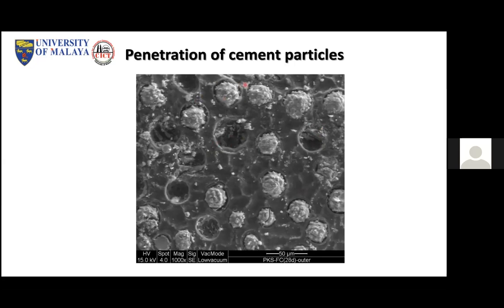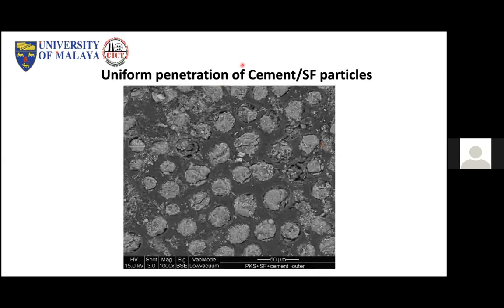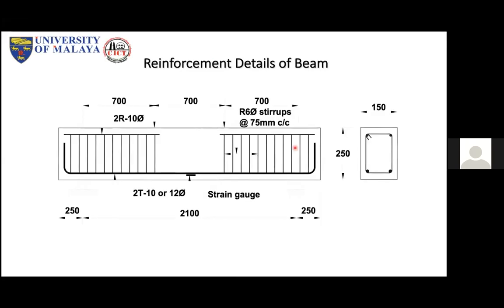You can see the filled one is the cement particles. Some of the holes are not filled with the cement particles. So because of this, we added silica fume particles. Then you see that more or less all the holes are filled with the silica fume particles. So this enabled us to get good bonding between the aggregates and the concrete.